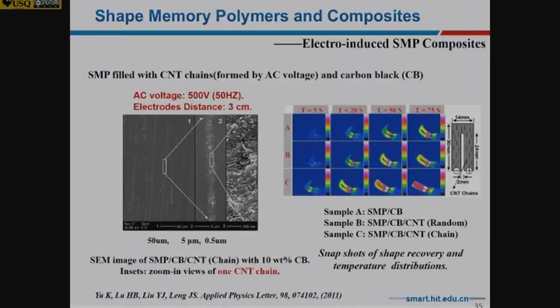And also we tried using carbon nanotube. The idea is we use AC voltage to align the nanotubes in the polymer. You can see, zooming from here to here, the nanotubes can form a chain. So after the chain is formed inside the polymer by AC voltage, you can simply apply voltage. During heating, you can heat the polymer to deploy.